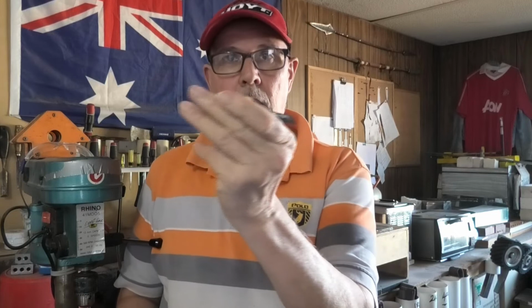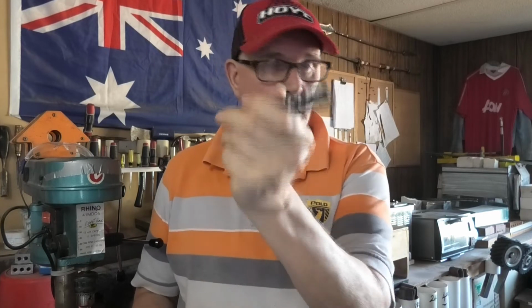Now it's interesting because yesterday when I did this, I treated this one to 1036 C, and I found it was the hardest one out of all of them. So it does lend itself to confirm what this is saying in here. Okay, so how I interpret this is the preheating and equalizing process is the kiln itself. So actually take it up to 1725. Well, let's just go with centigrade, because that's what I'm going to use here. Take it up to 940, hold that for 20 minutes, and then stick your steel in there, ramp it up to 1037, and then soak that for 15 minutes.